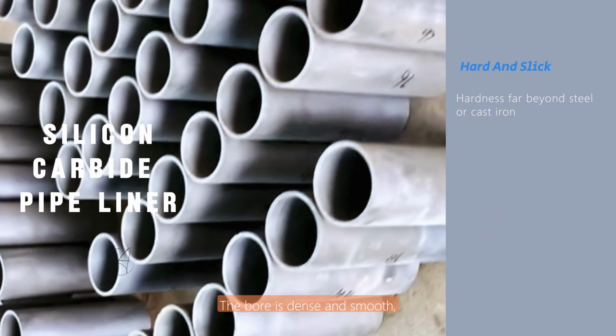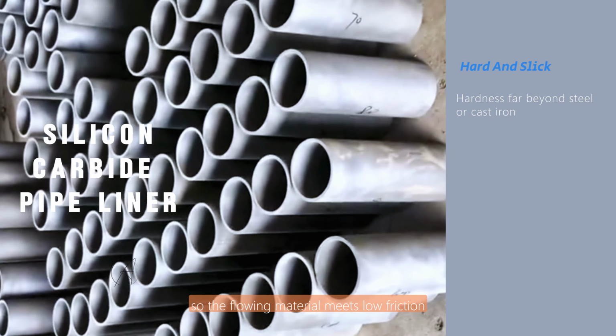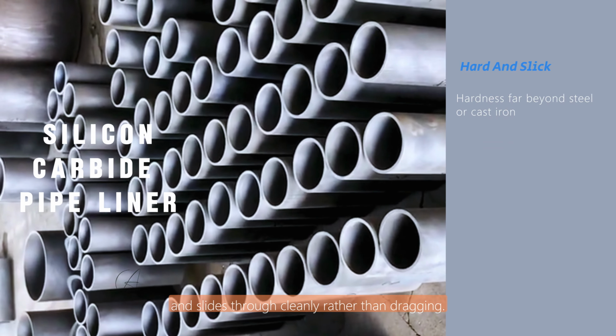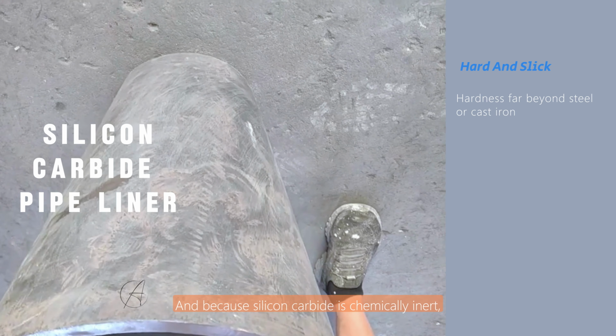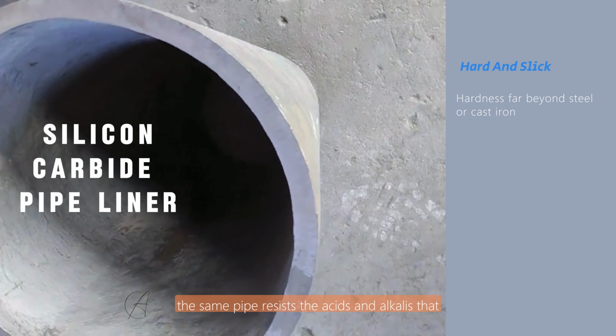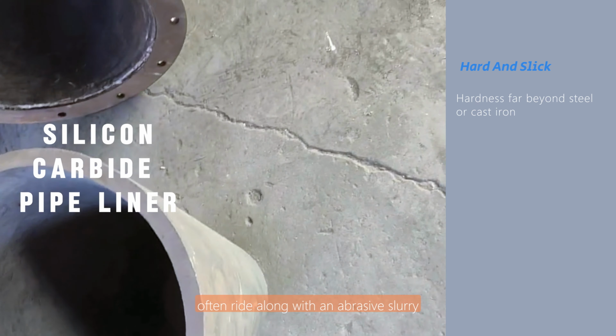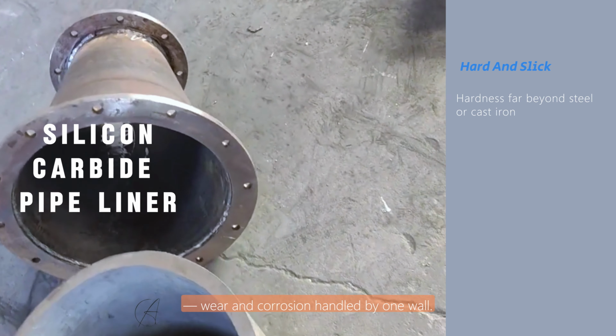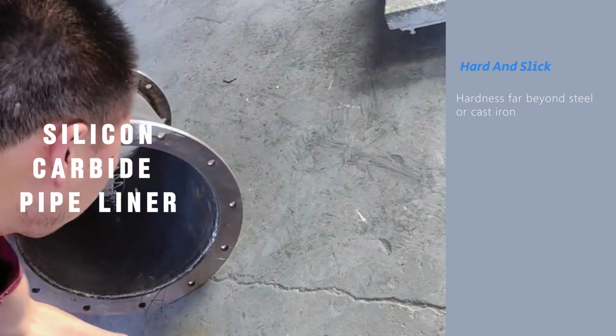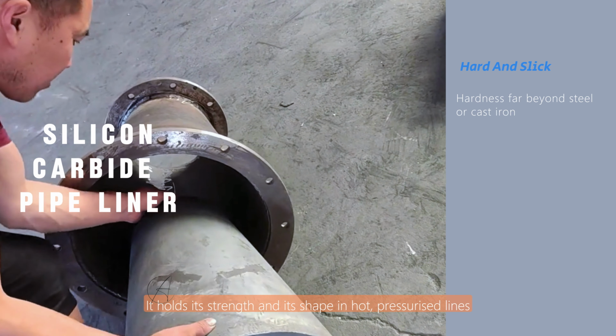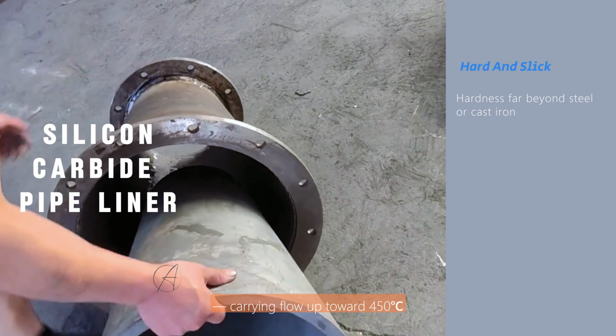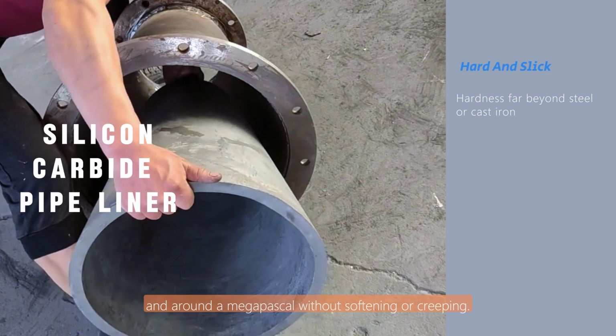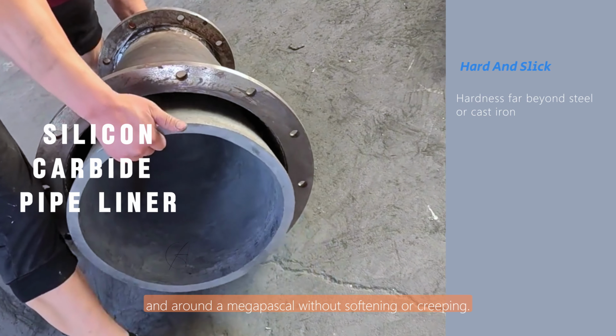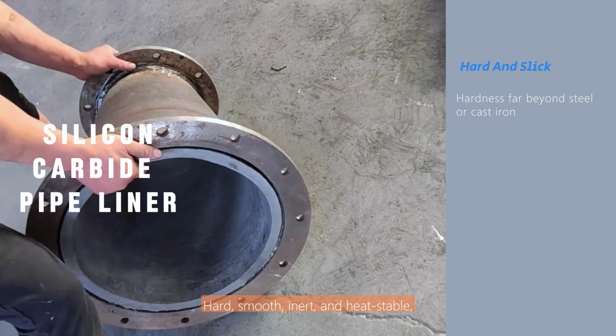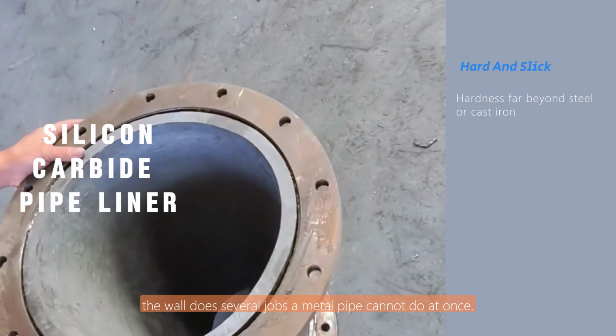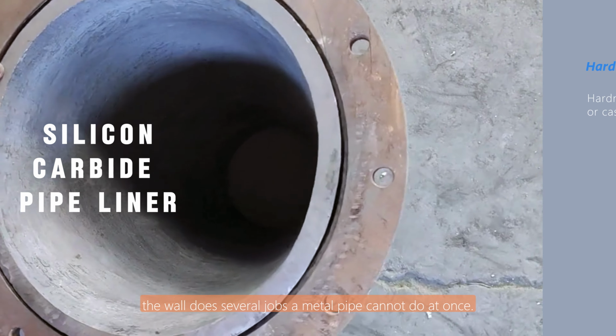The bore is dense and smooth, so the flowing material meets low friction and slides through cleanly rather than dragging. And because silicon carbide is chemically inert, the same pipe resists the acids and alkalis that often ride along with an abrasive slurry, wear and corrosion handled by one wall. It holds its strength and its shape in hot, pressurized lines, carrying flow up toward 450 degrees and around a megapascal without softening or creeping. Hard, smooth, inert, and heat-stable, the wall does several jobs a metal pipe cannot do at once.